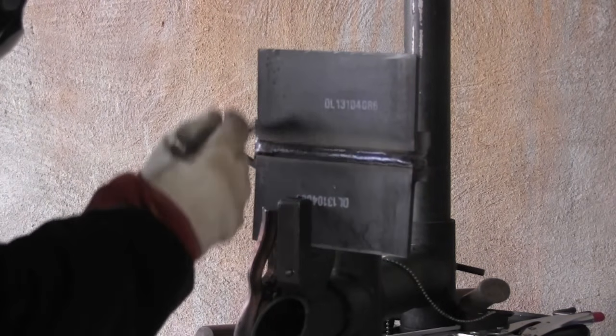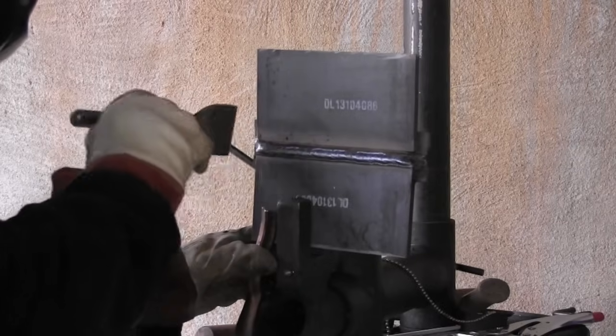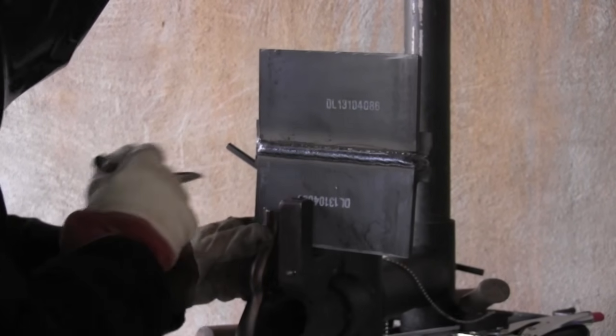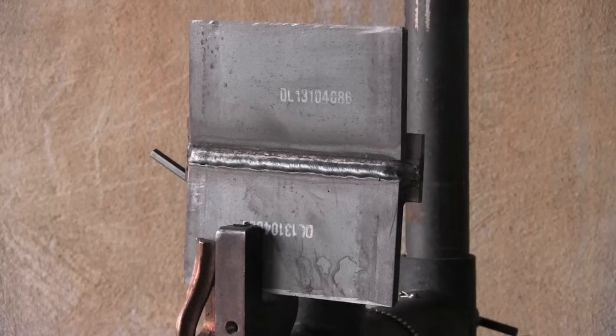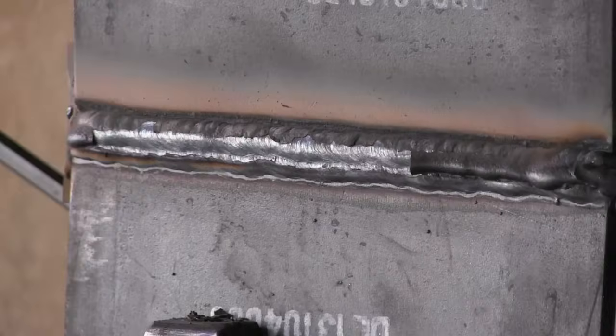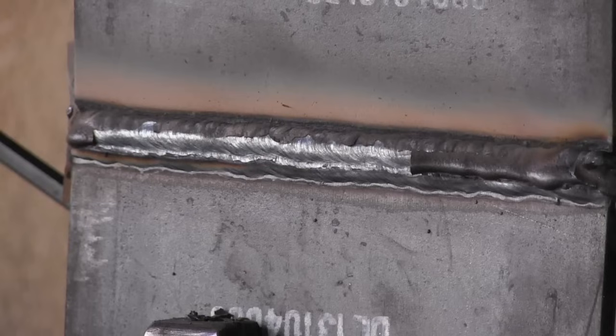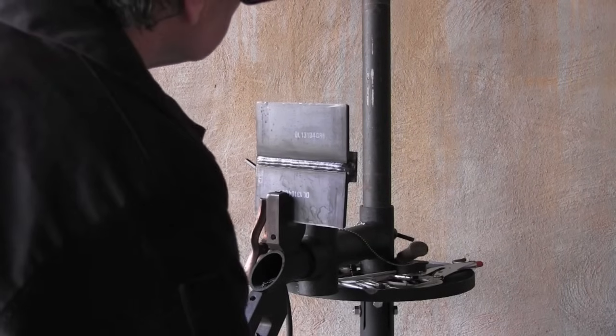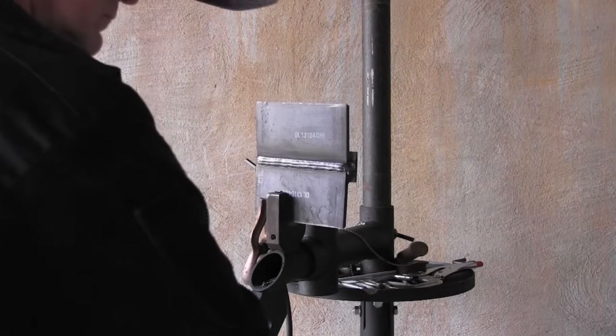I didn't get shots, forgot to turn the camera on to get arc shots of this first bead here, but you can just refer to that padding beads video. At this point it's just like padding beads on a flat plate pretty much, except for that last bead of trying to keep it straight and not get undercut. I intended to run that one kind of slow to give myself a little platform to stack the second bead on. I kind of messed up. I didn't overlap it enough and that leaves a little valley. I should have come down at least another sixteenth of an inch lower. That would have prevented that valley and would have made the whole thing look better.